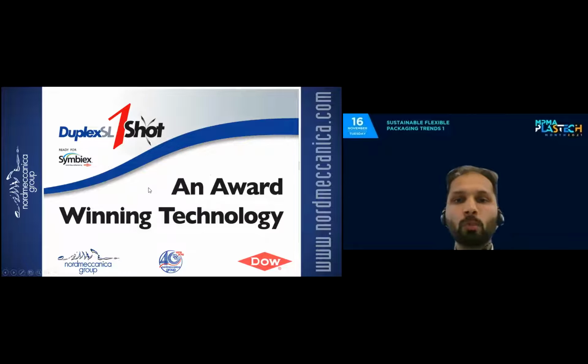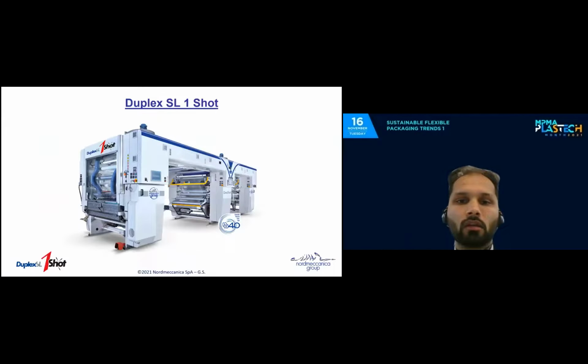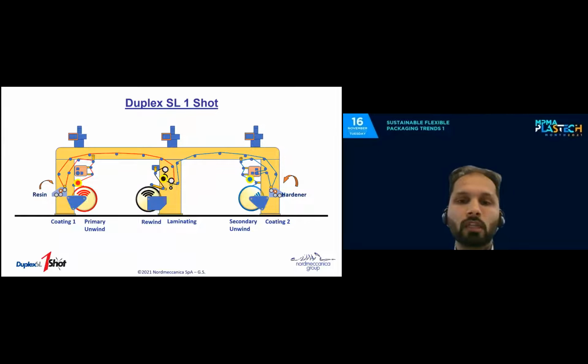Here you have another example, the Duplex One-Shot, another Nordmeccanica award-winning technology, which has been brought to the industry in collaboration with Dow, with the Symbiex technology. And how does this machine work? Here we have again two coating sections. But the key feature of this machine is that the two components of the solventless adhesive, the resin and the hardener, are applied on two different coating sections. So there is no mixing unit involved. The resin and the hardener are applied onto separate heads and are mixed together at the laminating unit. And here, after the laminating unit, the reel finishes up at the rewinder.